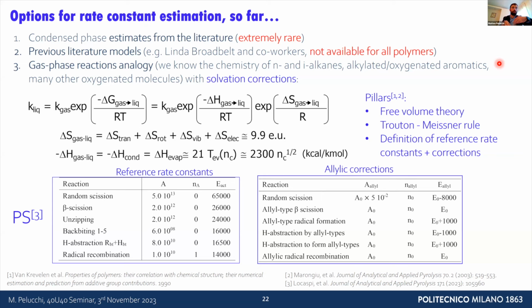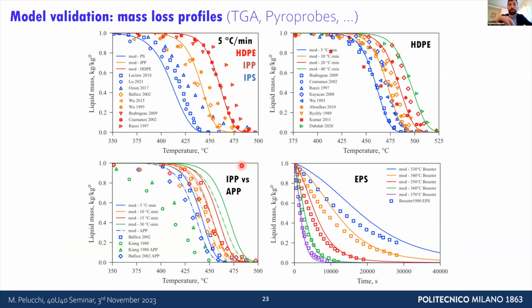Corrections from the gas phase and corrections for specific moieties that you may find in a polymer. So, for example, polystyrene will have many different allylic sites that will react completely differently from a normal polymer backbone that has only, let's say, primary and secondary, mostly CH bonds and CC bonds. This correction can be applied also, for example, in the case you want to distinguish between isotactic, bottom left figure, and atactic polypropylene. So we can take these features into account.